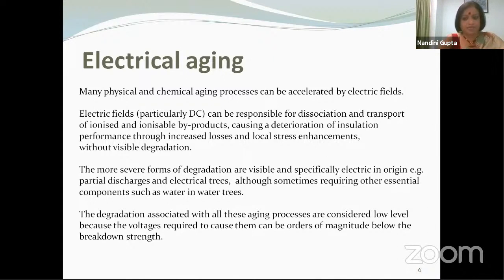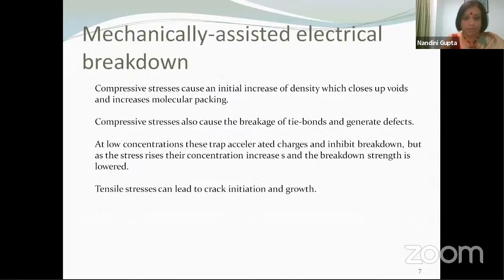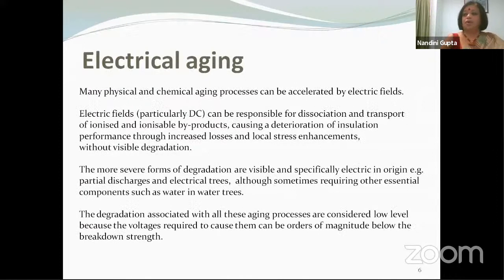The degradation associated with these aging processes are considered low level, and that includes the degradation due to PD and electrical tree. They are called low level degradation. The reason is that all these degradation processes happen at electrical stresses lower than the breakdown strength. So the breakdown strength that would cause the material to actually move towards failure is much higher than the electrical stresses which cause these degradation processes. So these are like incipient degradation processes which seem to be okay, but which are inexorably driving the material towards breakdown, because ultimately that is what will happen. Everything is hunky-dory. You are working at electrical stresses which are well below acceptable values, and at the same time you are actually moving towards an ultimate catastrophic failure. And that is the kind of process that we are interested in today.